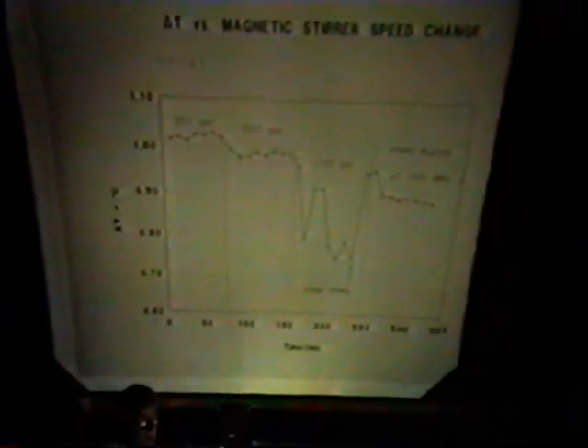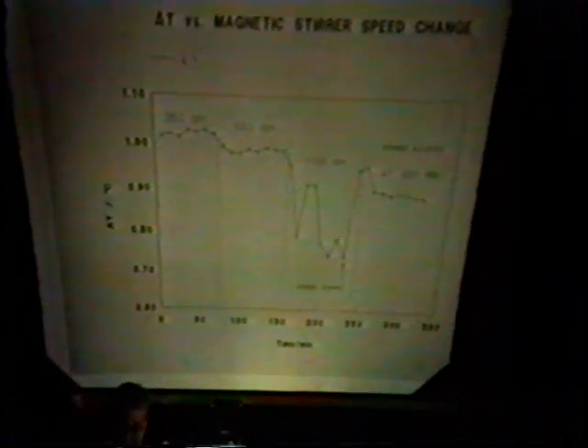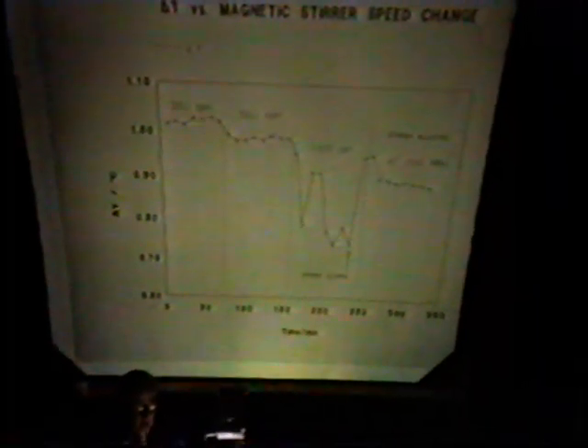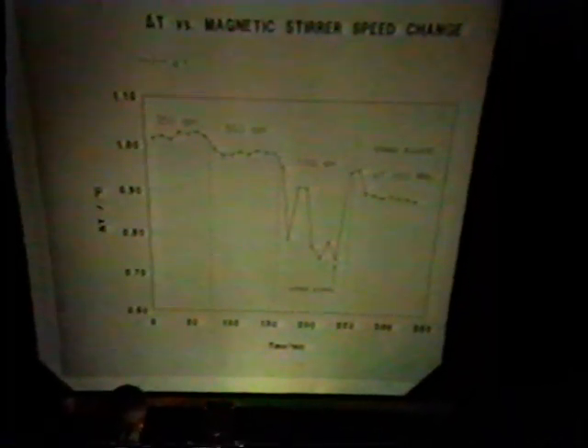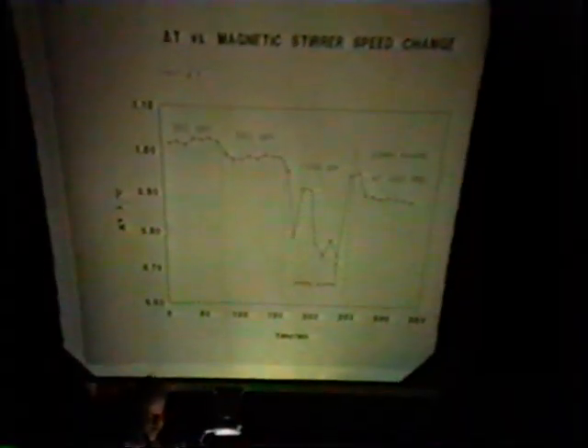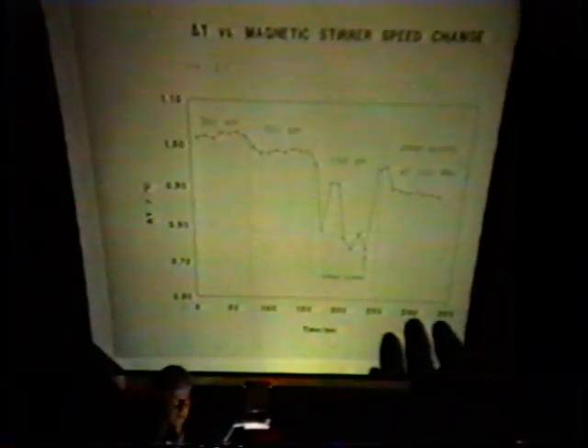We do have some difficulty with the stirrer. When the stirrer changes its velocity, which it does sometimes, then it affects the temperature. We have to be extremely careful about that. That's the graph of stirrer speed versus temperature. And of course, one is afraid of false results. These things all go on during the night. Texas A&M has its own electricity works. Suppose they change potential during the night, etc., etc. But you see, if there's a speed up, the temperature drops by 0.2 degrees or something like that. So it's only if the stirrer stops that we get a pseudo-burst. And the pseudo-burst is very great. Most of our bursts have been measured during the day, and of course we can see the stirrer.